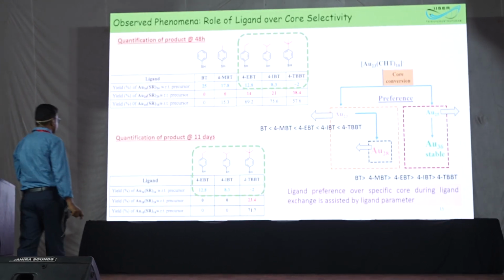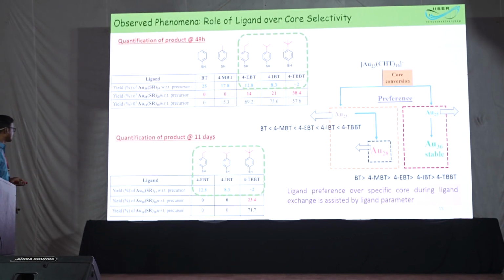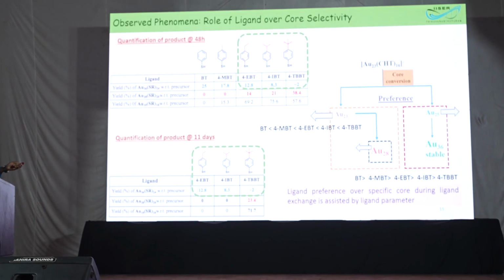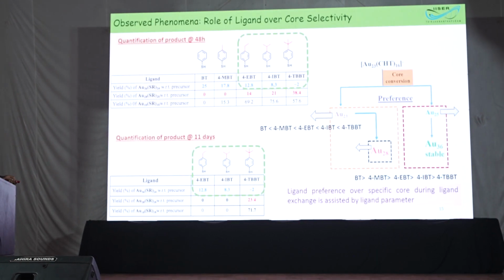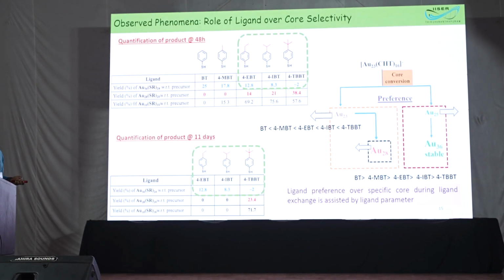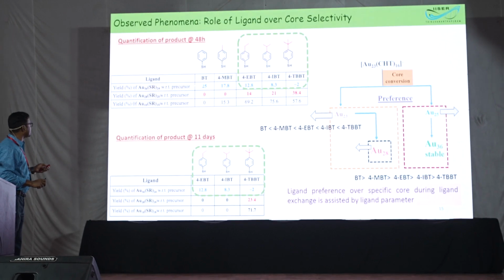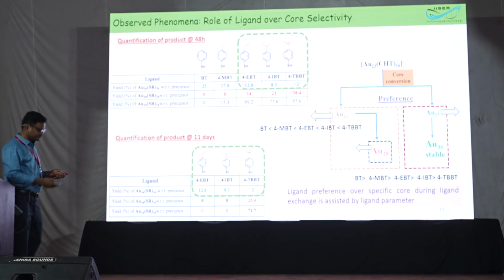We extended the reaction for 11 days. We can see that the 36 contribution for these three is not changing because the 28 is degraded. So 28 is not contributing. So whatever formation is happening, 36 is forming from a different pathway.